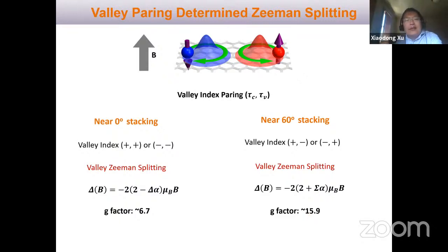So what this tells us is that the G factor of these narrow line emissions is determined by the twist angles. This is also consistent with the Moiré superlattice, because like I told you, the properties of these excitons should inherit the crystal lattice structure. It has nothing to do with defects, which should not be determined by these twist angles.